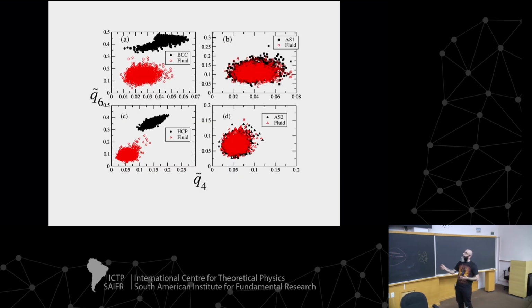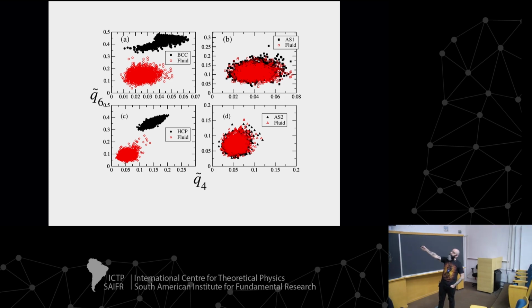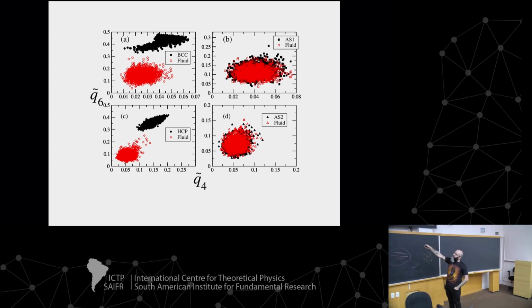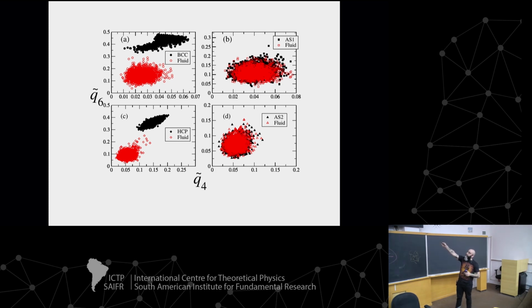Okay, we will also evaluate the orientational order parameters, Q6 and Q4. And we can see, this is really nice. When you have the BCC to fluid transition, the orientation of the molecules changes completely. So Q6 and Q4 basically give me an idea about the number of neighbors of each molecule and their orientations. So you can see that when I go from an ordered solid phase to a fluid phase, they are really, really different. When I go from an amorphous phase to a fluid phase by heating the system, they are practically the same. What's happening? Basically, they are gaining mobility as I go from the amorphous to the fluid phase. I will show it later.